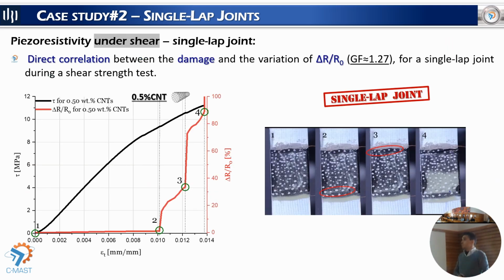After, we perform the shear test in a single lap joint, so we test until the rupture of the joint. And in this image, we can see and analyze what happens to the joint during the test. Once again, the black line is the mechanical data, and the red line is the electrical resistance. And here we can establish some correspondence between the different moments that happen during the test. In this image number 2, we can see the beginning of the fracture of the joint.